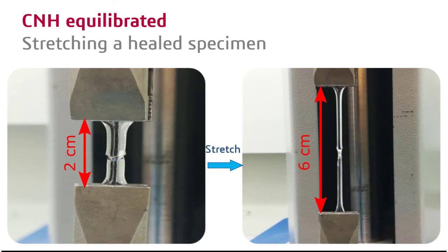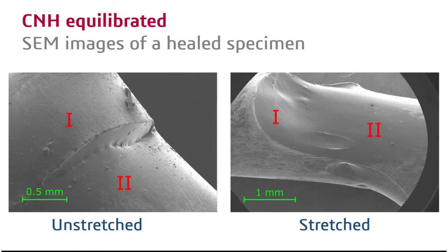In this image, you can see the behavior of a healed specimen being stretched. Now you are watching images of the healed sample obtained by scanning electron microscopy. These images certify the self-healing capabilities of our CN hydrogel in equilibrated state. Comparing the mechanical properties of the self-healed samples with the virgin ones, we obtain good results.